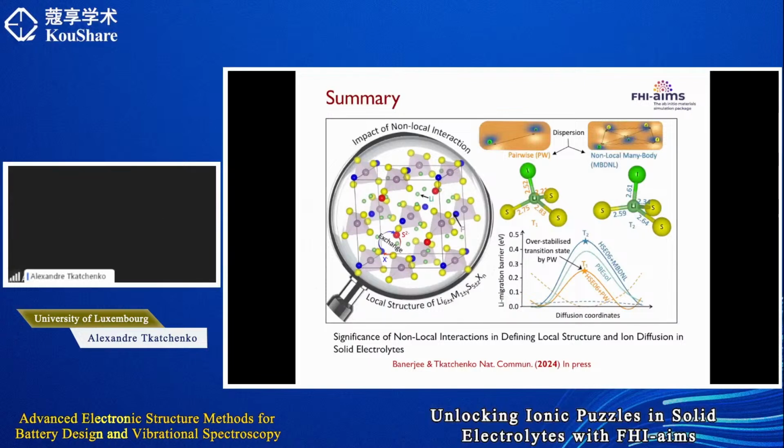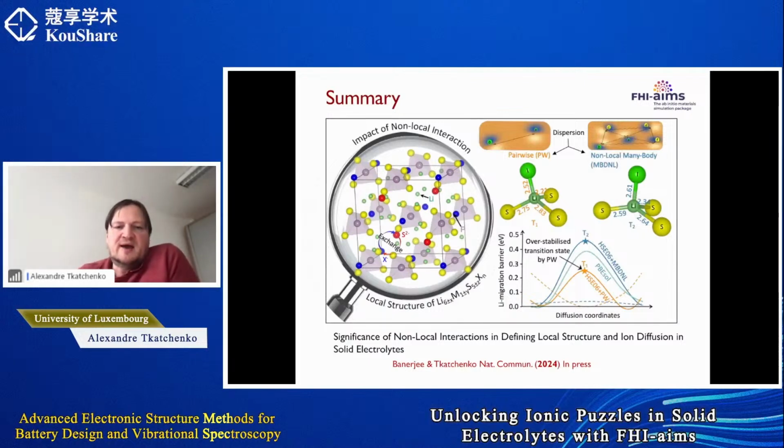Yep, this brings me to my conclusion. I have described a range of comprehensive calculations that we have done to understand different properties of solid electrolytes, in particular the argyrodite family. We found that the impact of non-local interactions, both in the exchange by using the HSE functional and in the long-range correlation by using the MBD-NL approach, has a high impact on both the stability of these frameworks and the mobility of lithium ions through the framework.